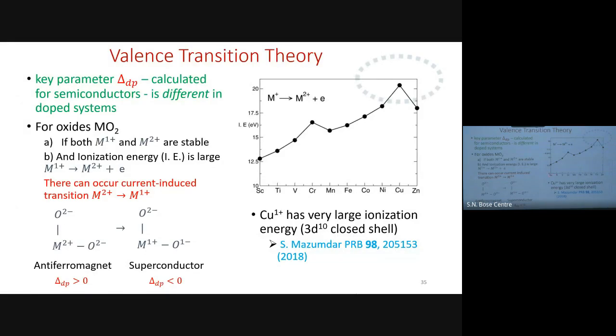So here I'm plotting the total ionization energy of the 3d elements. And you can see there is a peak at chromium, which is easily understandable. There is a very large peak at copper 1 plus. Why? Because copper 1 plus is 3d10. Closed shell ions have very large ionization energy. This term is going to be greater than 0. It will favor lower charge under certain conditions. So that is when I can go from here to there, and my site energy has become less than 0.